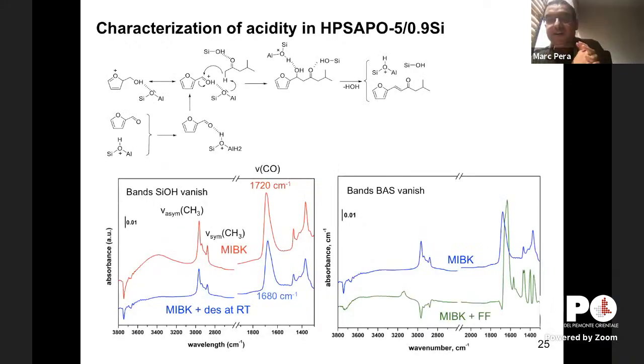Also, with the help of the skills of our colleagues from Alessandria, we were able to elucidate a little bit the mechanism of how this aldol condensation reaction takes place. And it seems that there are two sites participating, one acid site that should be located inside the microporosity and one silanol outside in the mesoporosity, outside the microporous zone.